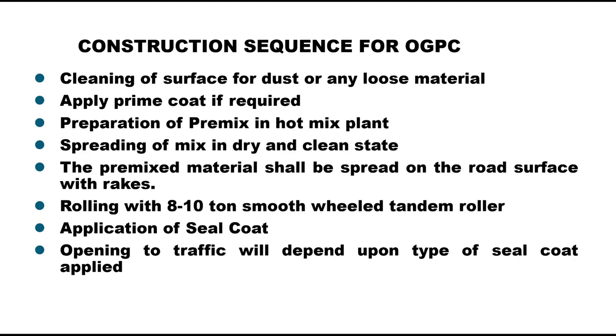For laying premix carpet, the underlying surface should be cleaned of dust or any loose material. Apply prime coat if required; if it is a granular surface, provide a layer of prime coat and tack coat as per requirement. The premix material is prepared in a hot mix plant for large works, or a mixer of suitable capacity for small works. Mixing shall be thorough to produce a uniform mix, and the mix is then transported to the point of use.